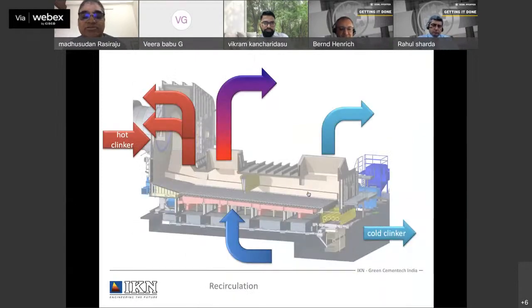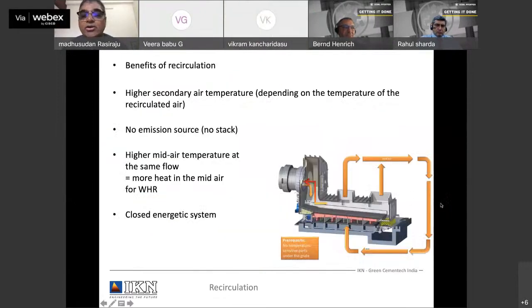And another challenge we faced is the cooler recirculation system. What happens when the industry started demanding high WHR power from the cooler? We had a challenge. The high efficiency cooler will automatically have less heat in the vent. So with less heat, we will not be able to generate the power which conventional or low efficiency coolers will generate. So what IKN did was, we took mid-air or hot air from the vent and recirculated it back into the cooler underhead chambers. And by doing that, we could enhance the WHR power considerably.